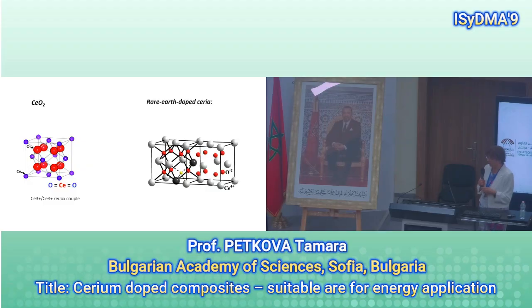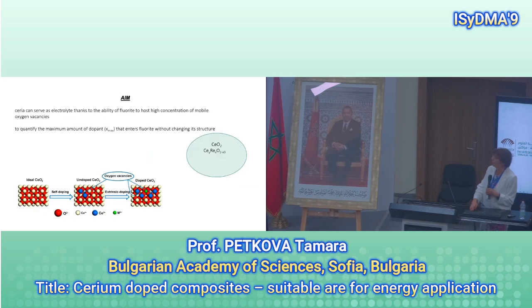It possesses a fluorite cubic crystal structure. It's important that cerium is in stable 4+ valency, but it can easily be switched to 3+, so it makes a redox couple cerium 3, cerium 4. If we introduce, for example, a rare earth or some dopant in this crystal structure, we expect this crystal structure to be destroyed or deformed.